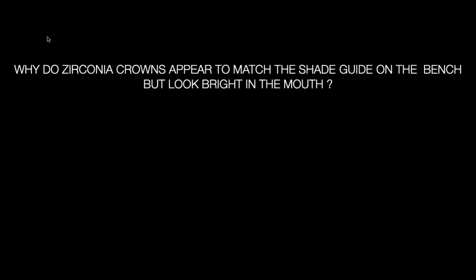And so what happens is if my target is, let's say, a 3M1, and I get these, they only have like 5 colors, and then none of them look like anything. And so I get them so they're quite a bit brighter. So what I do is I do a bonding layer with a much darker dentine, like a base dentine from a 4M1 or a 5M1, and look at it, and I'm telling you, it'll end up looking like a 3M1. That's how bright some of those abutments are.